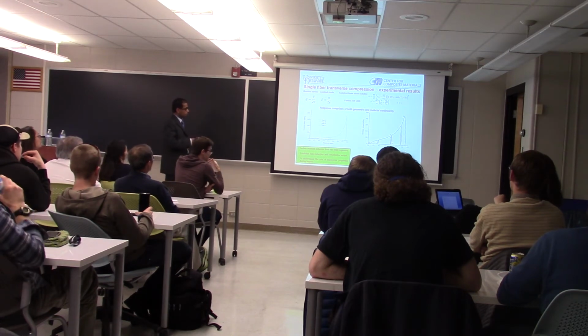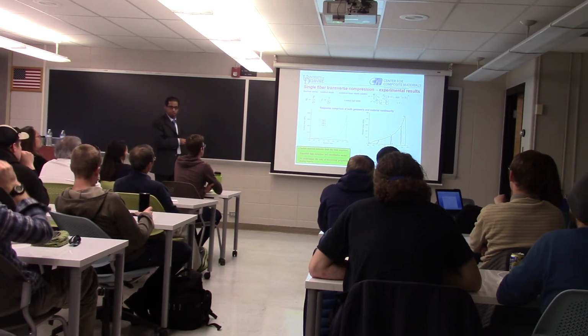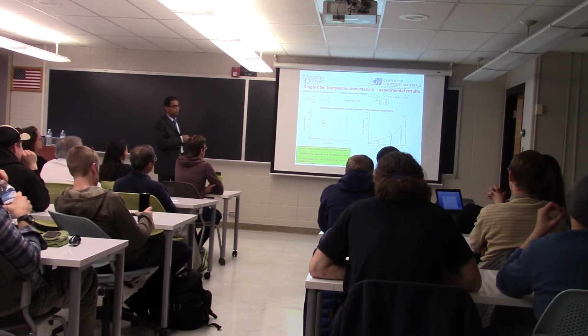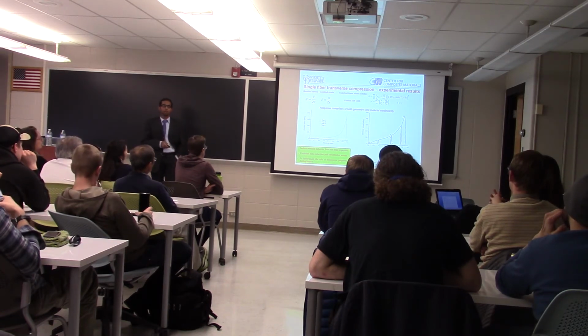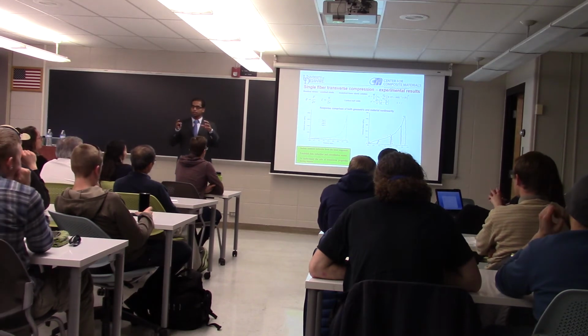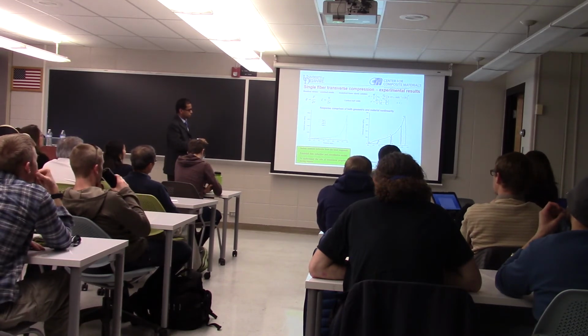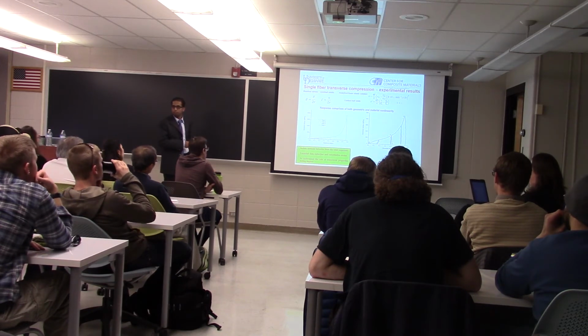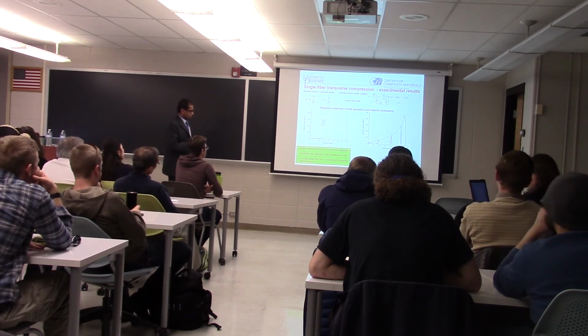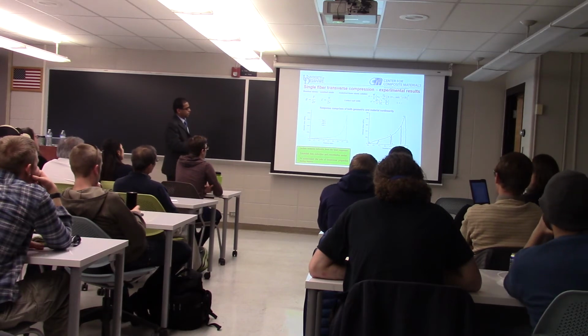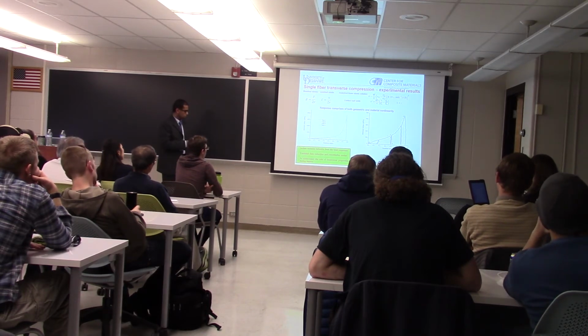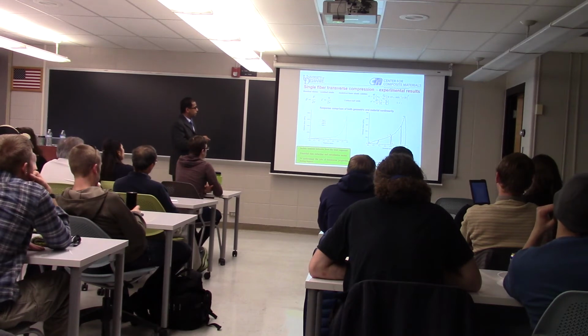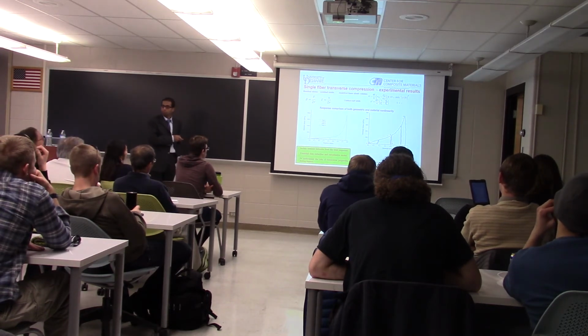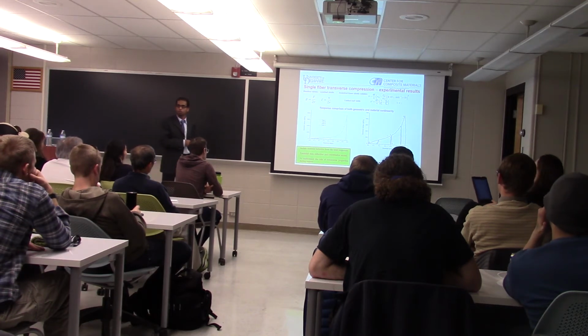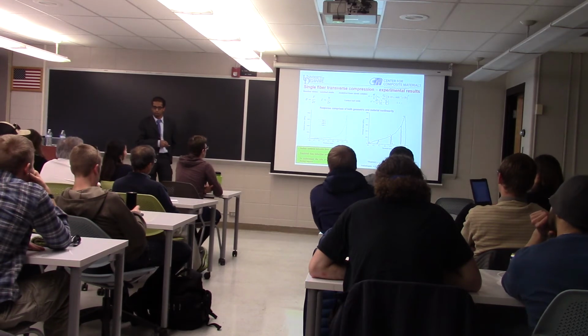So now the experimental response is clearly nonlinear and inelastic. And the response consists of both geometric and material nonlinearity. Geometric nonlinearity is due to the growing contact area, and material nonlinearity you can see from the permanent strains that we see from unloading. So the material accumulates large residual strains. Our objective here is to isolate the material behavior from the total response, because we need that to develop a constitutive model for the fiber that can be used in the modeling.